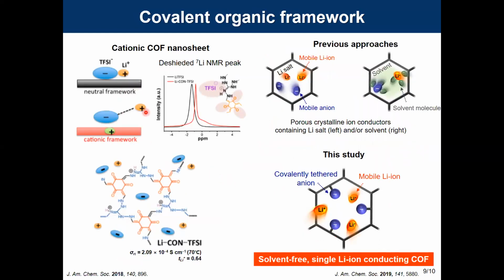And next, they demonstrate for the first time that a cation moiety incorporated into a skeleton COF material can easily split the ion pair of the lithium salt, boost the concentration of freely mobile lithium ions, and thus improve the lithium ion conductivity in COF-based lithium ion conductors like this. Notably, the cationic COF effectively screens the Coulombic interaction due to greater polarizability compared to a COF with a neutral framework.